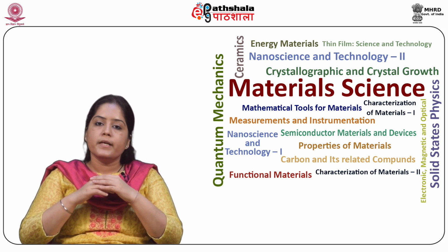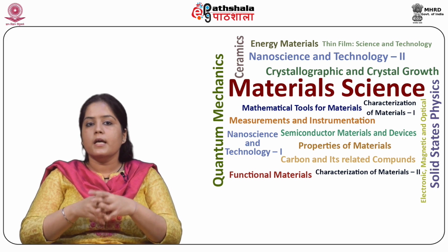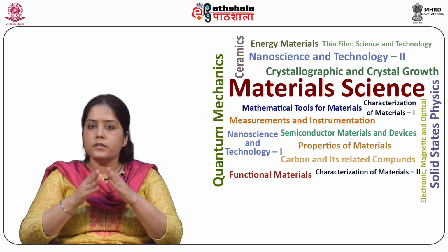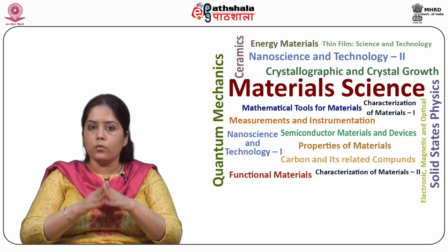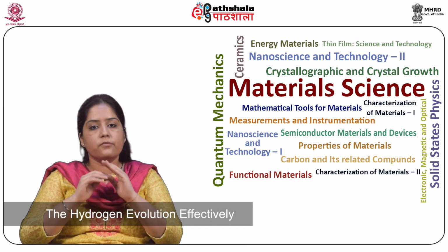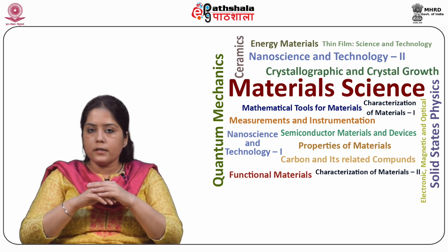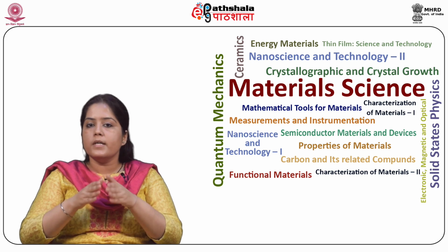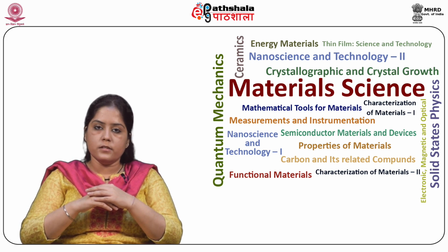For example, in zinc-nickel and zinc-air RFBs, a high hydrogen overpotential cadmium-plated nickel sheet has been used as the negative electrode to reduce dendritic growth and to suppress hydrogen evolution effectively. Three-dimensional nickel foam is another metallic electrode which has been used in sodium polysulfide-bromine and soluble lead acid systems.